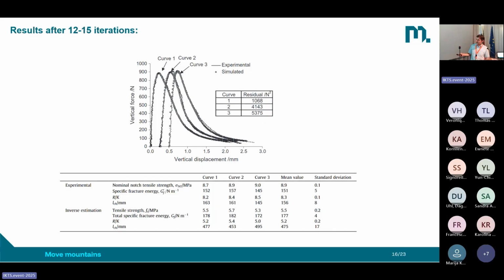Also, for the specific fracture energy, we see here 152 Newton per meter or joule per square meter, as you like it, and 178 from the simulation. So what is the difference here? You see from the experiment, we can only integrate the curve until we end the test. But for the simulation, we observe a higher value because the simulation assumes that we are going to the end. So from the input value, we are considering the whole curve.